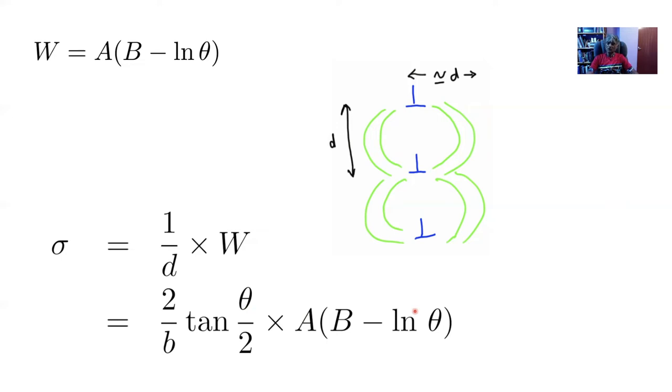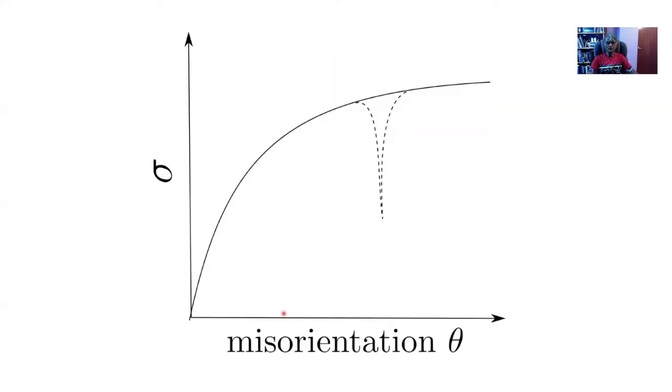So if we now plot that equation, it looks like this, that the variation in interface energy per unit area is rapid initially and then becomes more gentle. Ignore this for the moment. And the reason, of course, is that the interaction between dislocations as they approach each other in the array is large initially and then becomes smaller as they are close to each other. Eventually, it becomes meaningless to use this calculation because the core overlap doesn't allow you to use elasticity theory. And roughly speaking, this equation would break down when theta is about 15 degrees about a tilt axis.